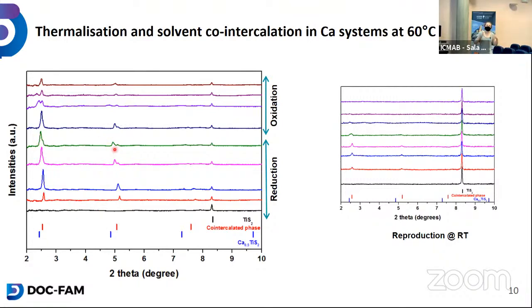But okay, the first phase to appear is the co-intercalation, just as lithium. And the second one is the intercalation of calcium. So that only appears at the end of the reduction. Upon reoxidation, you lose the calcium intercalated phase, as you can see here. And the co-intercalated phase also loses intensity. However, we were not able to complete the reoxidation on this cell.